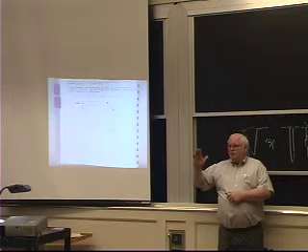Anyway, if you know which direction you want it to move, you actually make it move even further away when you heat it. And people say, oh, you're heating in the wrong spot. And then when you let it cool down, it actually comes back in the direction you want. So one of the problems is you have to have room for it to go even further in the direction you don't want it to go when you heat it to bring it back, which sometimes is a problem.